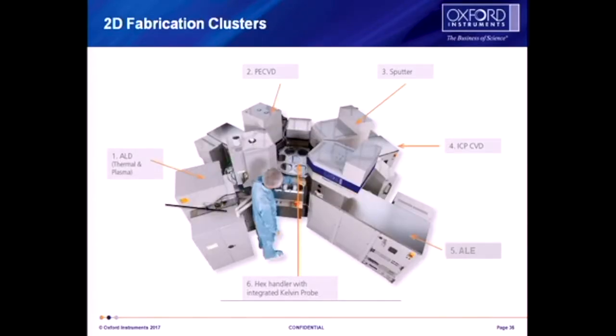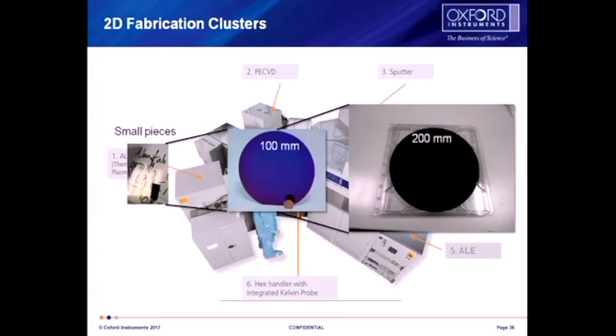And if we wished, we can cluster a lot of tools together to make these chambers all quite separate, and that makes it scalable. So you can do research all the way through without breaking vacuum, which keeps the device surfaces and the interlayer surfaces very clean, with no oxygen contamination. We've gone from small pieces. This is actually plasma graphene, which is only done at 200 mm, but 100 mm as well.